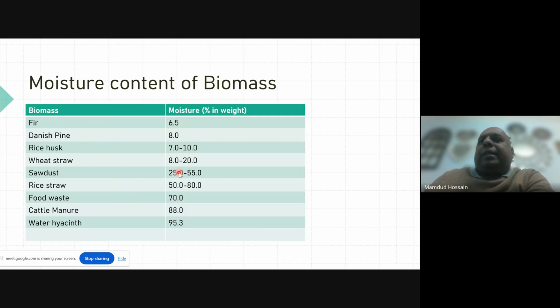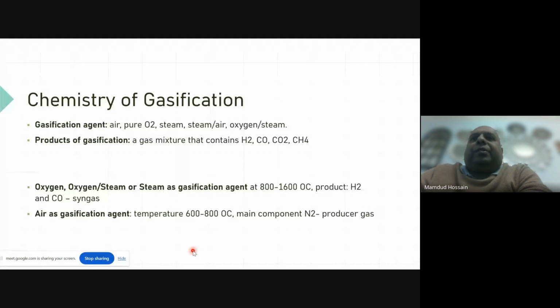So water content varies significantly in biomass. If you heat it, most of the heat will go into vaporizing moisture. In terms of the chemistry of gasification, we can use air, pure oxygen, steam, a mixture of steam and air, or oxygen and steam as a gasification agent.